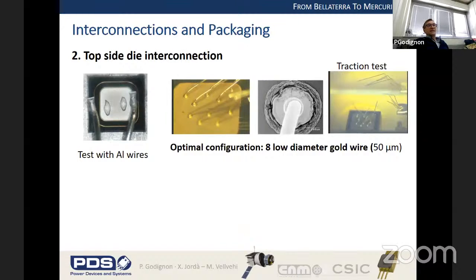Another step is the topside interconnection of the component. So originally we used the typical wiring system. So we use aluminum wire, but definitively with the high thermal stress and cycling we need for the BepiColombo mission, this wire was not able to sustain the stress and lifted after a given time of stress. So we had to switch to a different solution, which was to use gold wire with a smaller diameter and to put more wire in parallel. And indeed, gold on gold solder is really the perfect solution, especially if you have high temperature cycling.